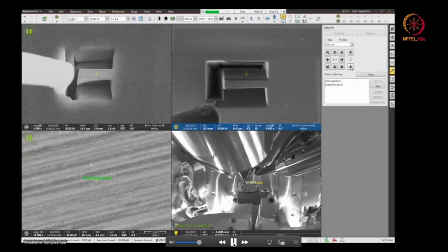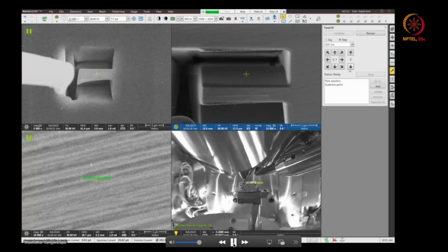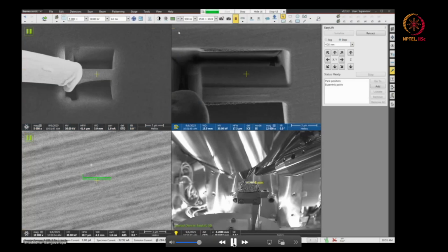Again, once you come very near to the sample, you can decrease the step size. Now the step size is around 500 nanometer, you can see, and slowly you have to move, and once you see it touch the sample, at that time you have to stop. So you can see in the E-beam window, it's almost touching, and in the I-beam also you can see it almost touching.